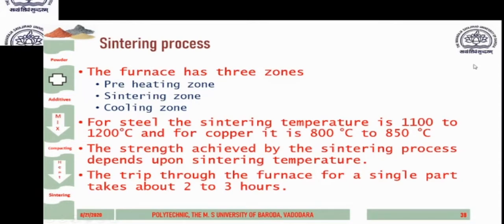The strength achieved by the sintering process, or by the component after sintering, depends on the sintering temperature. The trip through the furnace for a single part takes around 2 to 3 hours. That means starting from preheat, sintering and cooling, it takes around 2 to 3 hours or more, as the part or product component would require.